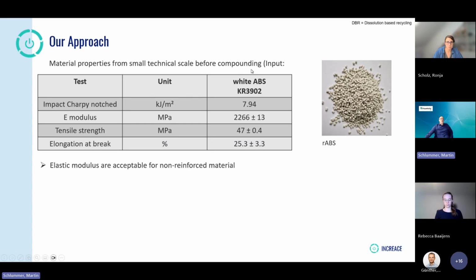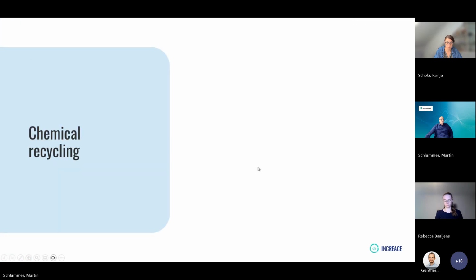Same story before compounding. Here, a very typical result is that the impact Charpy is far below what we normally measure for nicely virgin compounded ABS. But again, this is easily adjustable by adding new impact modifiers to get back to normal values here. So that's for solvent-based recycling, and let's switch over to chemical recycling.